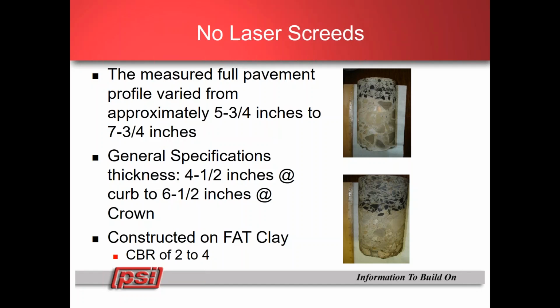We were able to obtain a few cores from the road. The cores that we obtained were approximately 5 3/4 inches to 7 3/4 inches thick, so they apparently exceeded the 4.5 to 6.5 inch thick requirement. The road is constructed on a fat clay subgrade having a CBR of 2 to 4, and there was no chemical modification or improvement to that fat clay.